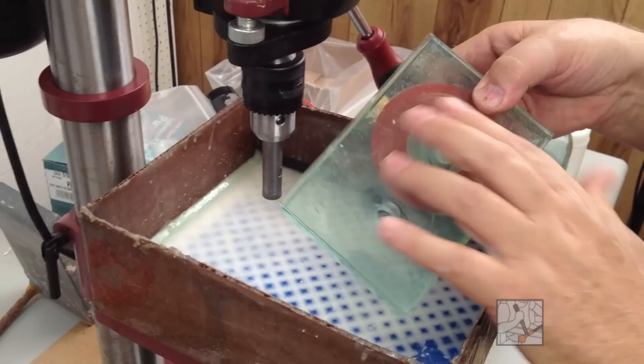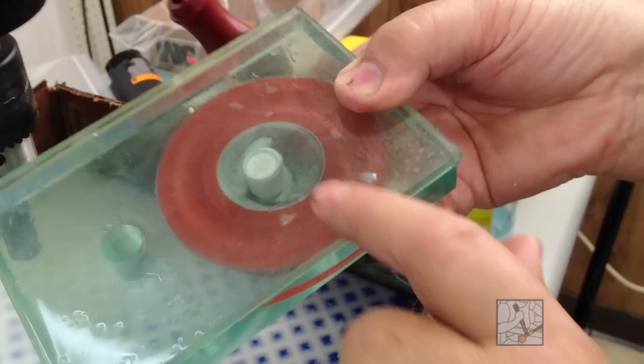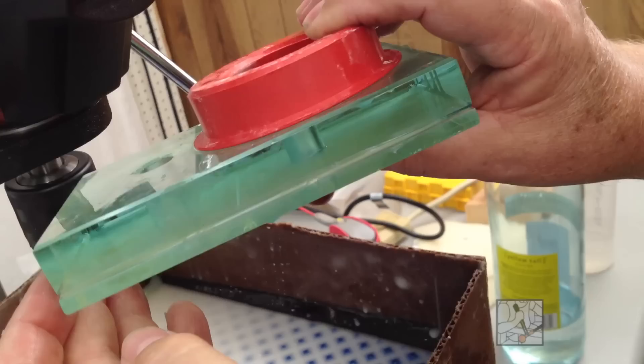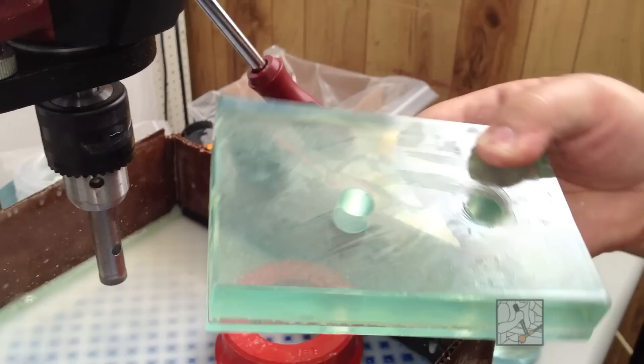And one thing you'll see is that I've just kissed the quarter inch piece of glass. If you look through you can see that it's just barely into it. You can see the top of the glass is not that bad but there is a little chipping in there. And when we take the waxed glass off you should find that the other side of this hole where we went through the witness glass first, the sacrificial glass, you should have a better surface.